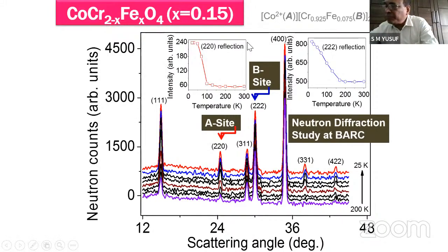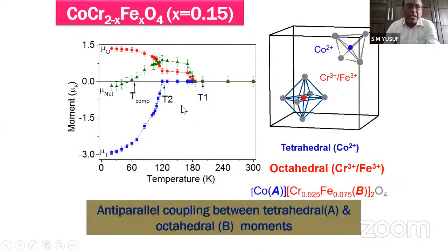Now from the neutron diffraction, as you see here, when we cool it, the intensity grows, and this is the intensity of individual Bragg peaks. And you see the tetrahedral site. This is the tetrahedral site magnetization as a function of temperature measured by neutron diffraction. And the red one is the octahedral site. But you must see one interesting observation here, that this is the magnetic ordering temperature, the so-called TC in DC magnetization study, what you see in the magnetization measurement. There, neutron diffraction tells me that only the octahedral site gets magnetically ordered. There is a spontaneous magnetization moment forming only at the octahedral site. But the tetrahedral site magnetic ordering takes place at a much lower temperature.